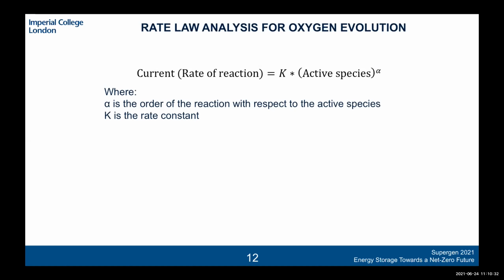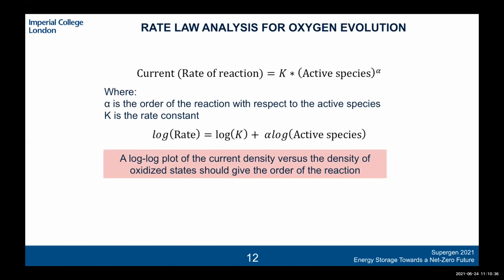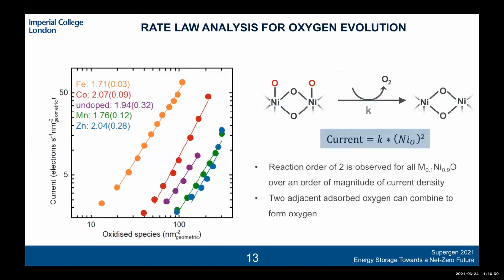So using quite a straightforward mathematical manipulation, we can see that if you were to look at the log of the rate versus the log of the density of these active species, the slope of that graph would then give you the numerical value of alpha, which is basically what we've done in the next slide here. So we can see on the y-axis, we have the log of the current density, and on the x-axis, we have the log of the oxidized species.